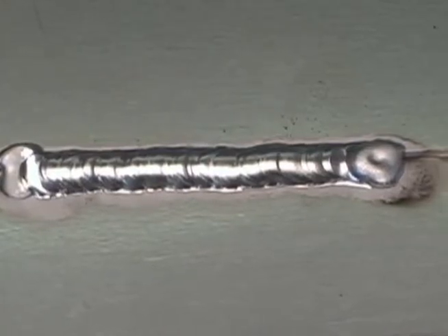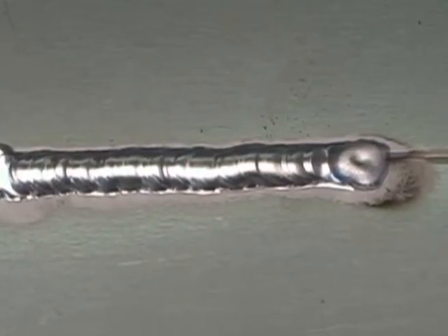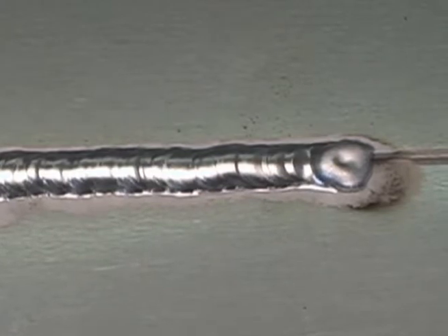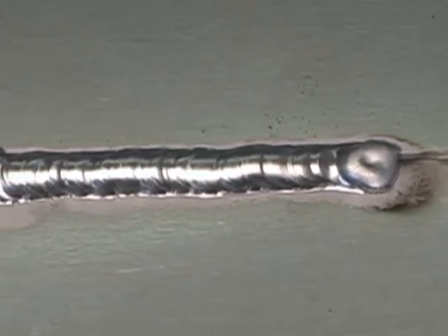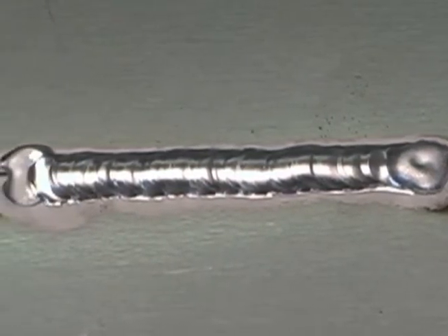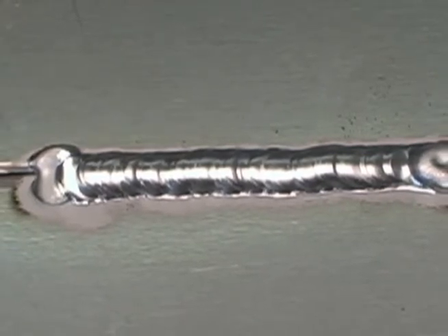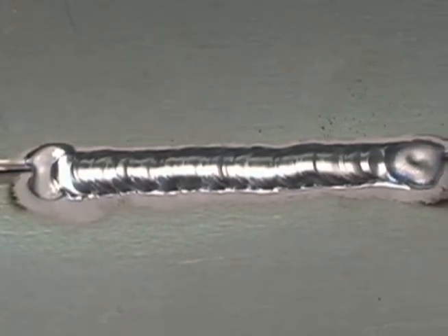Here is the finished weld. You can see a little bit of contamination at the end of the weld. Again, we should have done a better job cleaning the panels. You can see there is a very narrow heat affected zone and a nice consistent bead width.